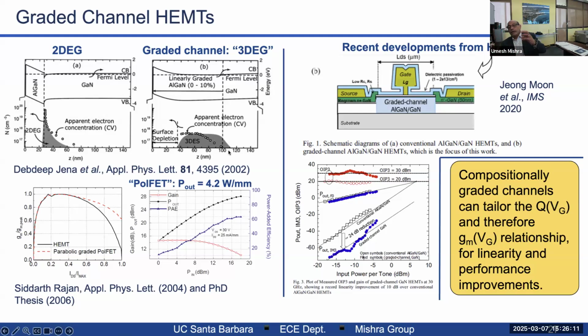And so then the PolFET, the minute you have a three-dimensional electron gas, it's a MESFET effectively without the scattering of the impurities that a MESFET needs. And you can actually change the doping profile by just changing the grading slope. So Siddharth Rajan, when he was a student here, made a HEMT and a parabolically graded PolFET, so you could change the GM curve. All very exciting. Recent developments from HRL: HRL uses this, and Jong Moon has pioneered this at HRL and gotten great linearity from these devices.